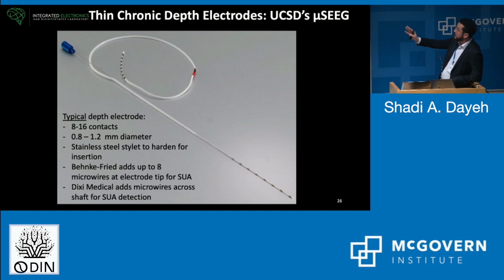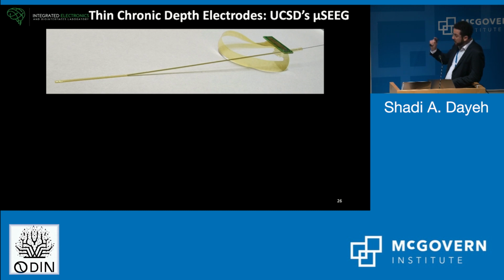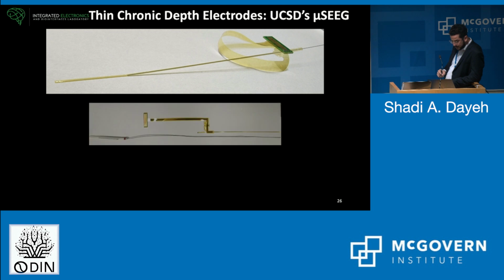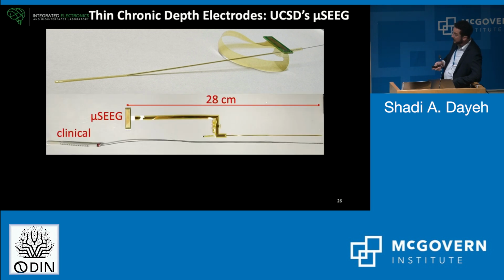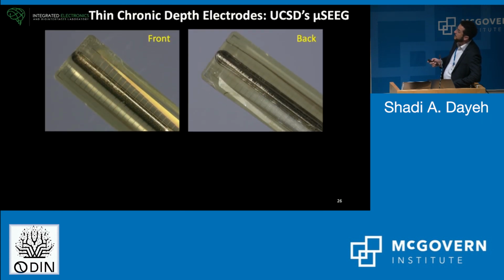Traditionally, to map activity or stimulate from deep brain structures, depth electrodes, such as the one that you see here, are about 1 millimeter in diameter, have up to 16 contacts, and are about 6 millimeters spaced, about 3 millimeters in length, either platinum or stainless steel. Leveraging the thin film microfabrication techniques, and to use a clinically compatible approach, we developed thin-film depth electrodes where one can insert a stylet to stiffen the electrode to implant it, and then the stylet can be extracted afterwards. This has a similar length, about 8 centimeters or so deep into the brain.